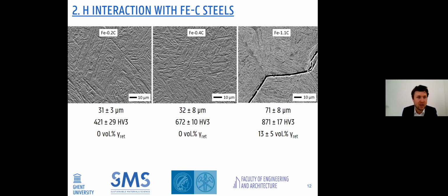For the 0.2 and 0.4 carbon material, this was completely possible, but since carbon increases the critical cooling rate, we had to increase the austenitization temperature for the 1.1 material. There we went a bit higher, we went to 1000 degrees as austenitization temperature for the 1.1 because we wanted to avoid the formation of second phases like troostite. So that's why the temperature of austenitization was a bit higher.